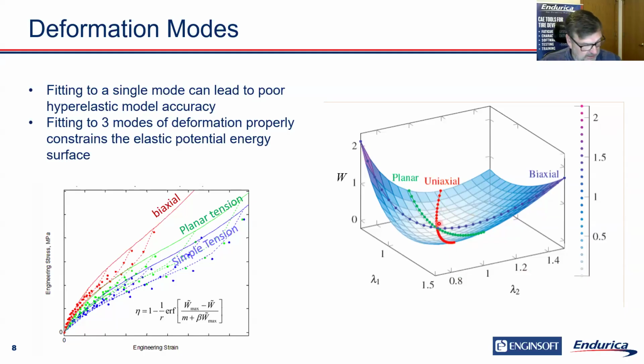So here we have uniaxial tension, like a small specimen like this. And then we introduce planar tension, which is a very wide and not so tall specimen that we'll pull in the vertical direction. And then an equibiaxial test that we'll do, which will give us a better idea of this overall response surface. Here we see some stress strain results for those tests in simple tension, planar tension, and biaxial tension, along with the amount that the rubber softens. So there's something called the Mullins effect, where if I pull it once, it softens, and the second pull is not as stiff as the first, etc.